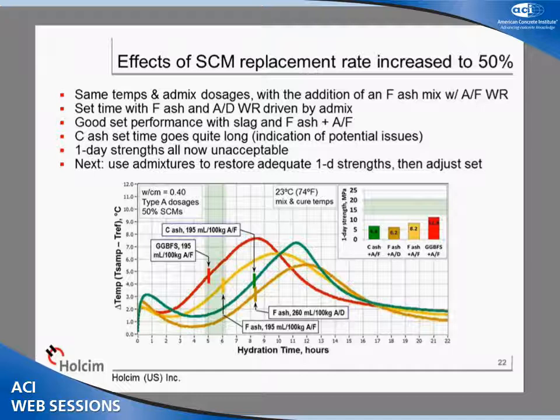I mentioned that the Class F fly ash mix with the lignosulfonate water reducer, the retardation from that has put that mix not on an even keel for competing with the others. So let's throw in a 4th mix that uses the same polycarboxylate as the other mixtures, and you see that the setting time effects are actually back into the target band for now, both for the F-ash and the slag cement. But the C-ash mix has a problem set time. So we're going to need to address those things.